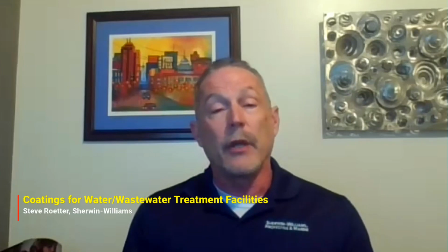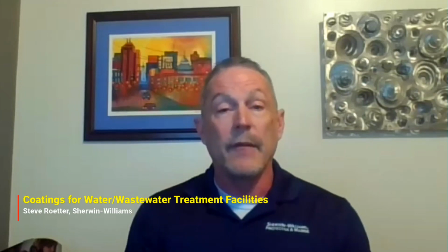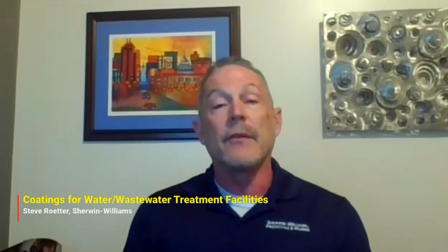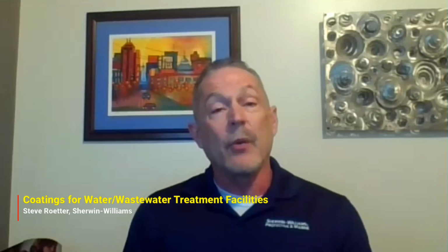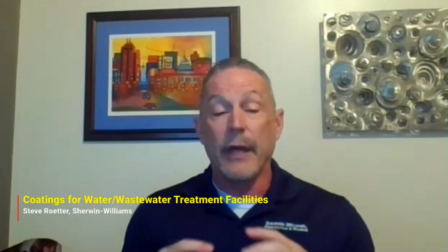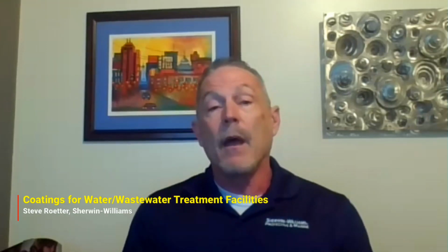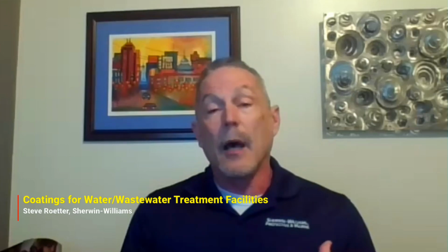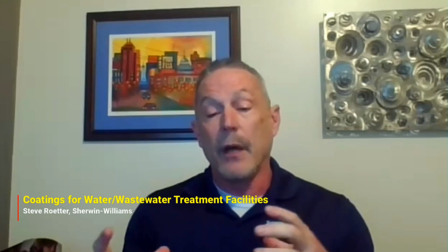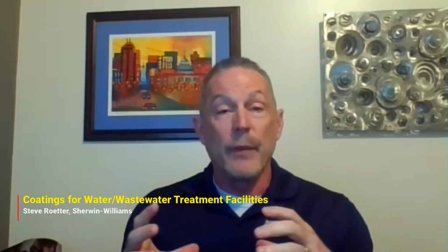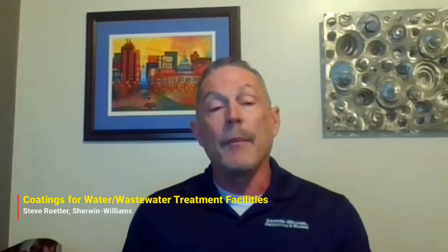So in general, for severe wastewater service, there's really two good options. The new generation of 100% solids epoxy coatings are really good, and they've been developed for these conditions. Some of these are reinforced with a microfiber or a glass flake to give them additional structural integrity and help to build the film thickness. And then you have the elastomeric polyurethane technology. If you have some movement in the concrete or some cracking, the elastomeric is a good technology.